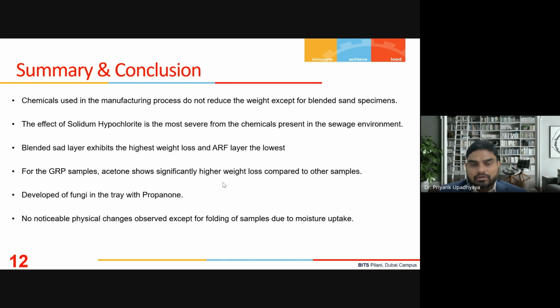In the case of sulfuric acid, it works as a hydrolysis agent, and some of the bonds in the polymers could be broken, and that's why we see some weight loss there. And we have seen a lot of weight loss because of NaClO, which behaves as an oxidizing agent. Because of that, again, the resin goes through damage, and that's the reason we notice these weight losses.